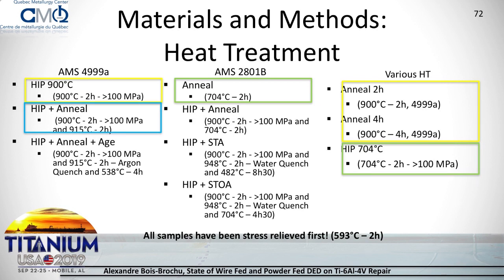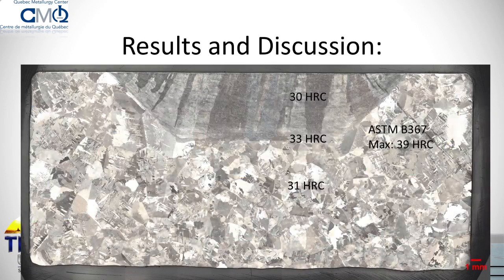And similarly, we've worked with the annealing at 704 within the 2801, but we also tested hipping at that temperature to evaluate the effect of hipping under such condition. As well, we tested various standard heat treatments such as solution treatment and aging, and solution treatment and overaging. So here is the actual microstructure of the repair.